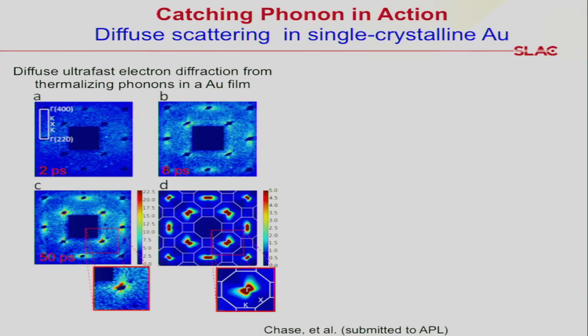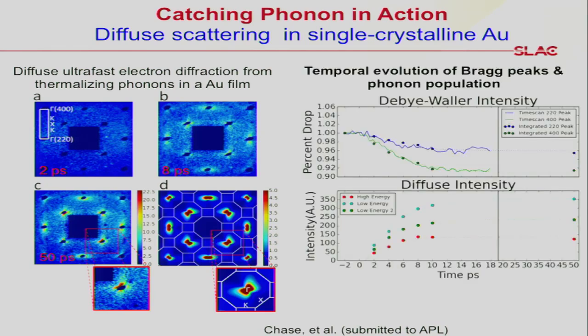So we compared our experiment at 50 picoseconds with the simulation. Around the Bragg peak, you see very good agreement. You may ask, what do you learn from this process? One of the things is how heat propagates in materials. You have a laser heating the material, forcing electrons to quickly heat up, then cool down with the phonon lattices. We learned that the dynamics at the Bragg peak are much slower than the phonons between the Bragg peaks. So there's a much more dynamic process than we saw.